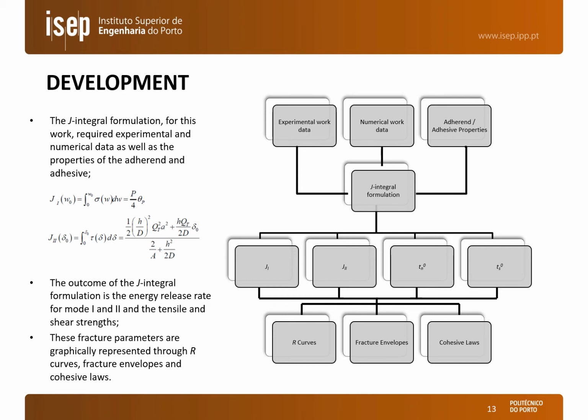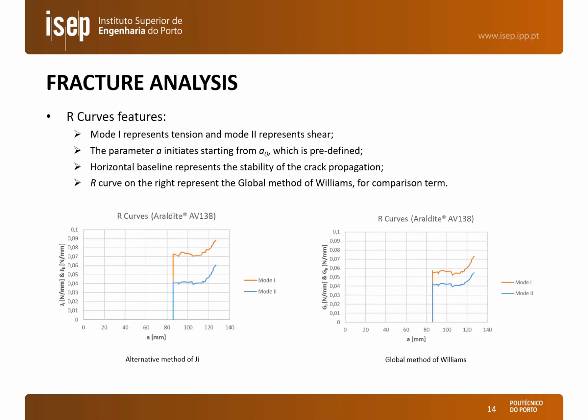We are going to use all of this data to formulate the J integral, and from this formulation we are going to obtain G1, G2 and the cohesive stresses Tn0 and Ts0, which all of this information together will give us the R curves, the fracture envelopes and the cohesive laws.